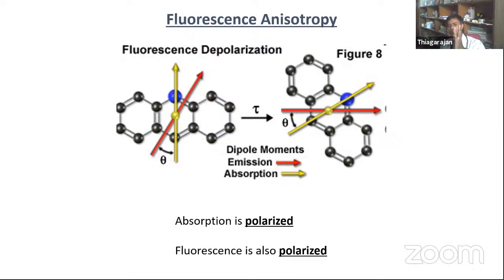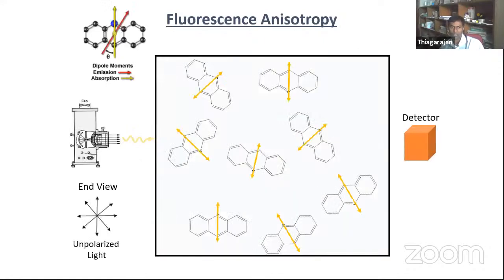During the lifetime of the excited state, the molecule oriented in this direction may rotate. Maybe it undergoes fast rotation or slow rotation. If the molecule undergoes very fast rotation, we cannot see it in the polarization anisotropy. But if the molecule is heavy and rotates very slowly, we are able to see it from the anisotropy measurement. Those kinds of things we can see. The molecules in solution always orient in different directions.